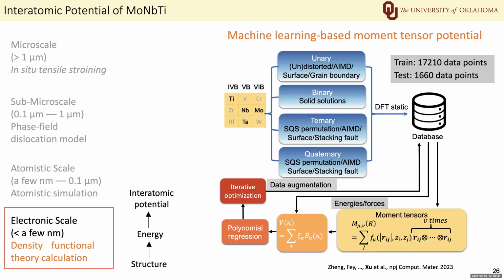So we then use the density functional theory calculation data to build an interatomic potential, which is fundamentally important to atomistic simulation. We chose a machine learning based moment tensor potential because it has an excellent balance between accuracy and efficiency.